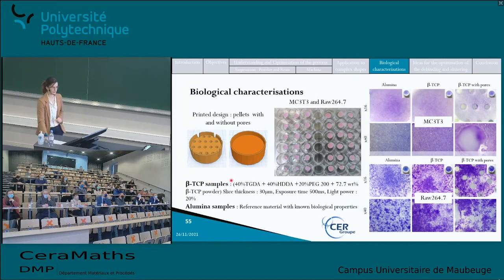So I used two different types of cell, MC3T3 and RAW 264.7 cells, which are pre-osteoblasts and pre-osteoclasts. And first, the repartition of the cells on the surface of the sample was observed with a microscope in order to see if the cells were staying on the sample. So the experiments were made with toluidine blue, which is colored in blue in the presence of cells. So this confirms that the cells stay at the surface of the sample. And here in the samples with pores, we can even see that the cells migrated inside the pores.